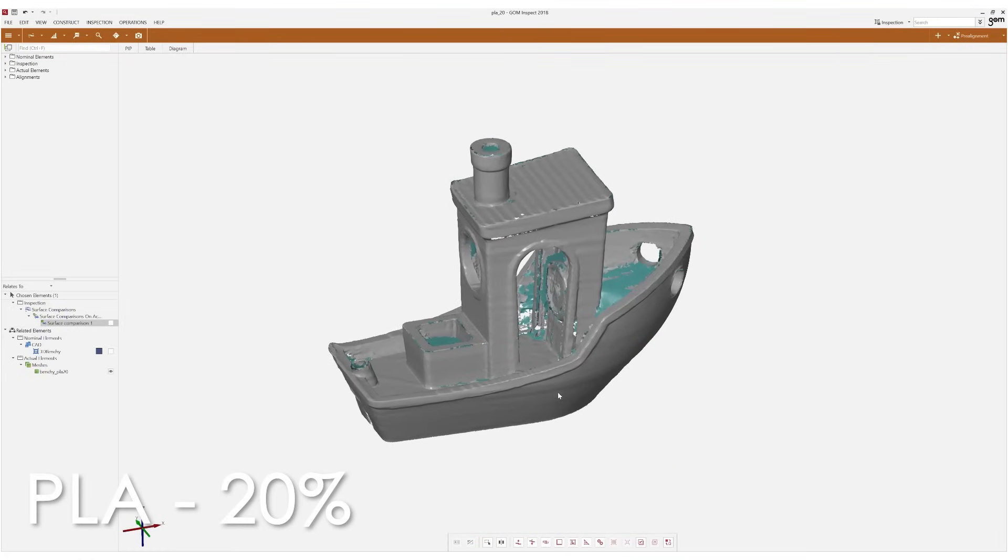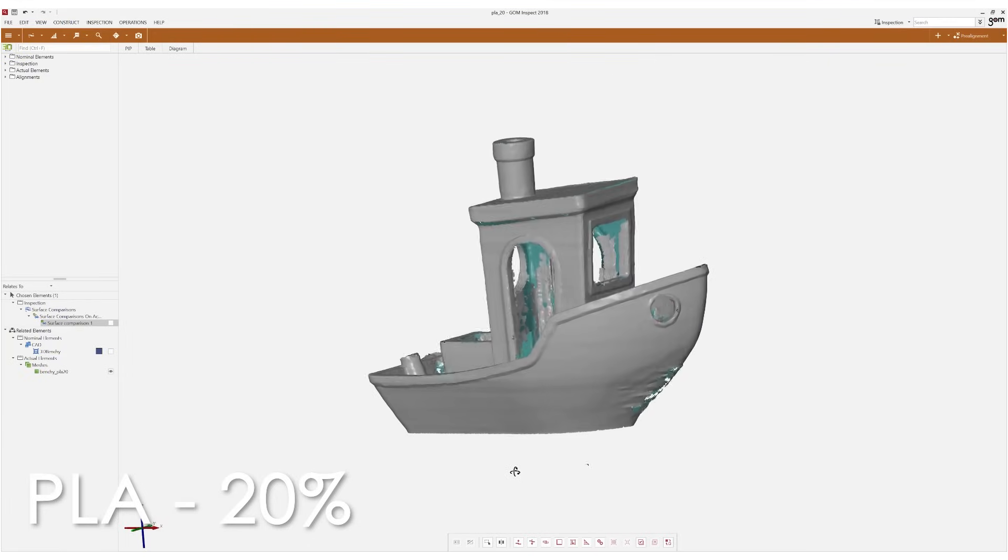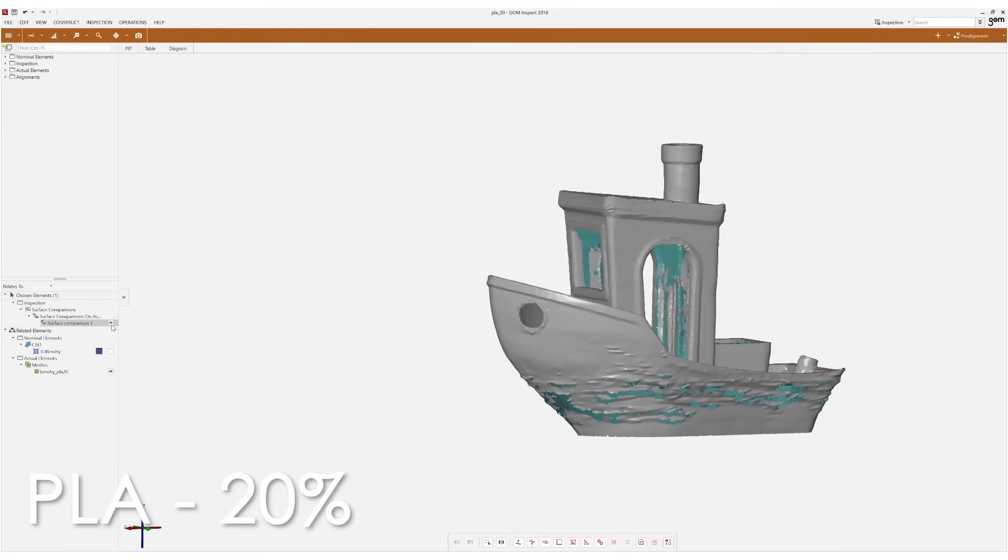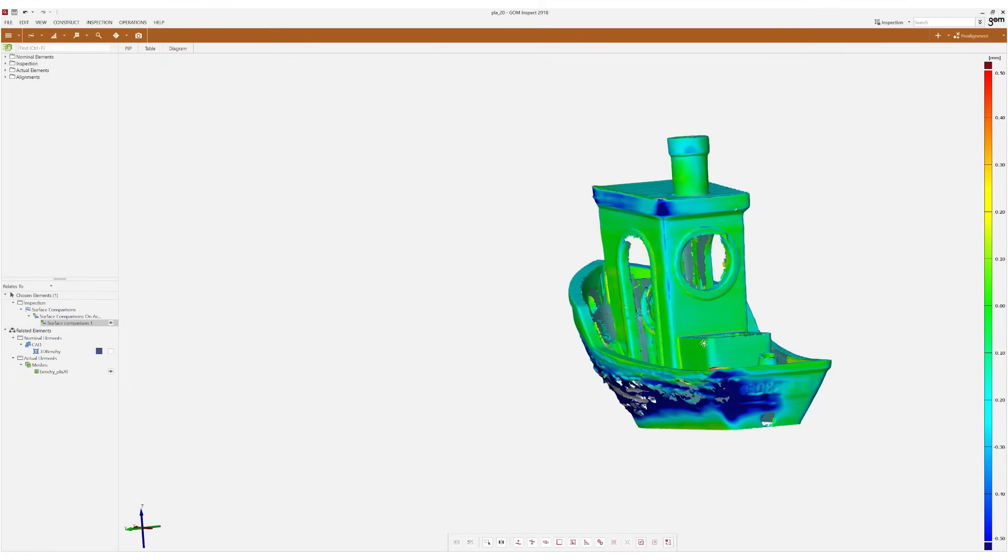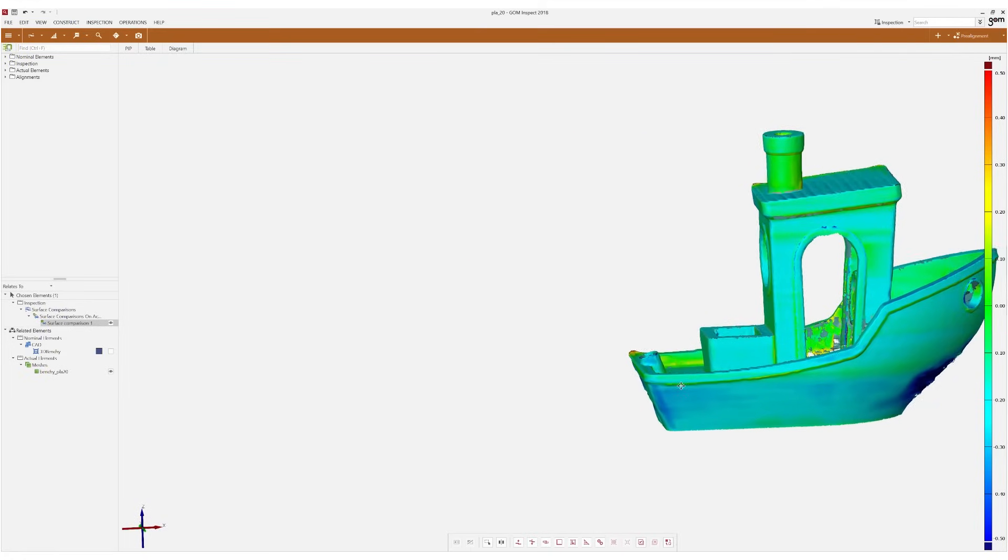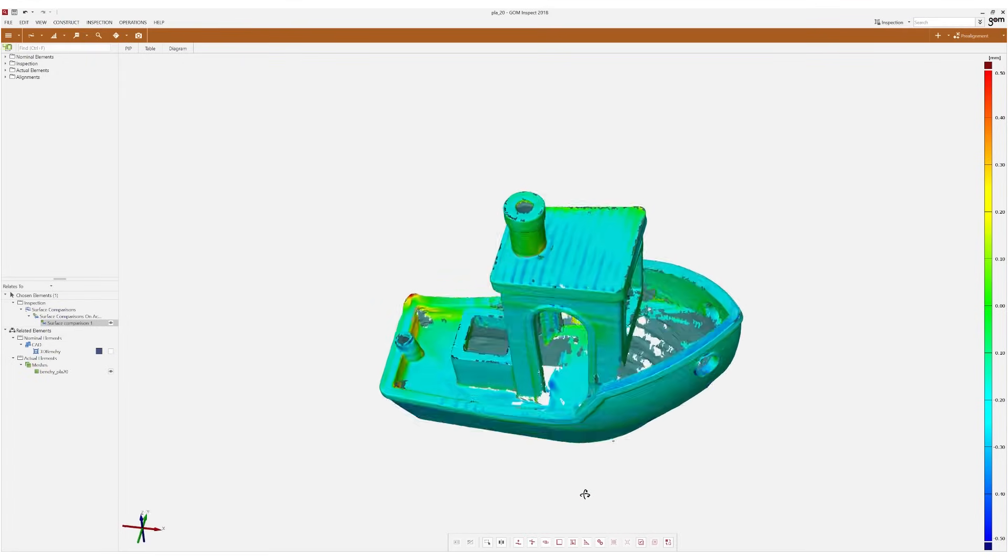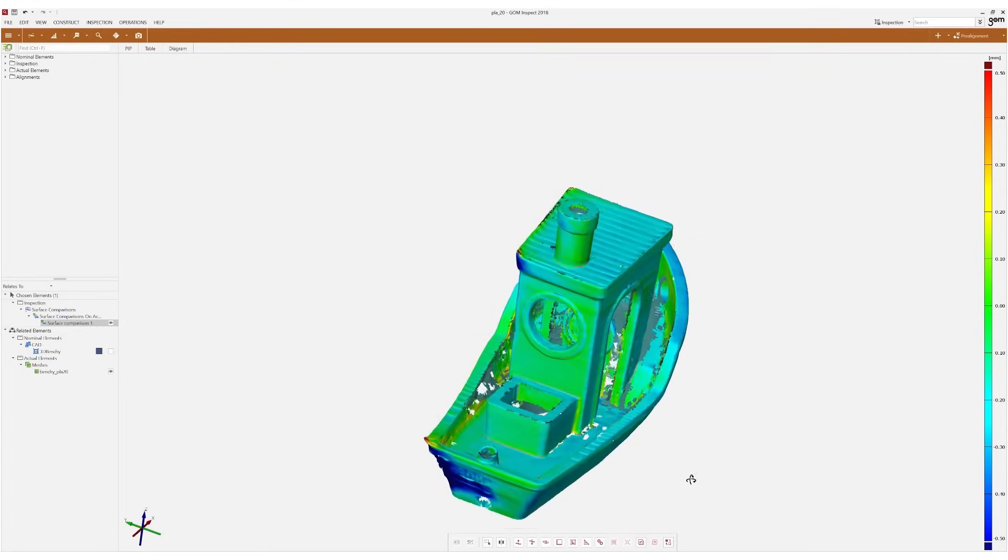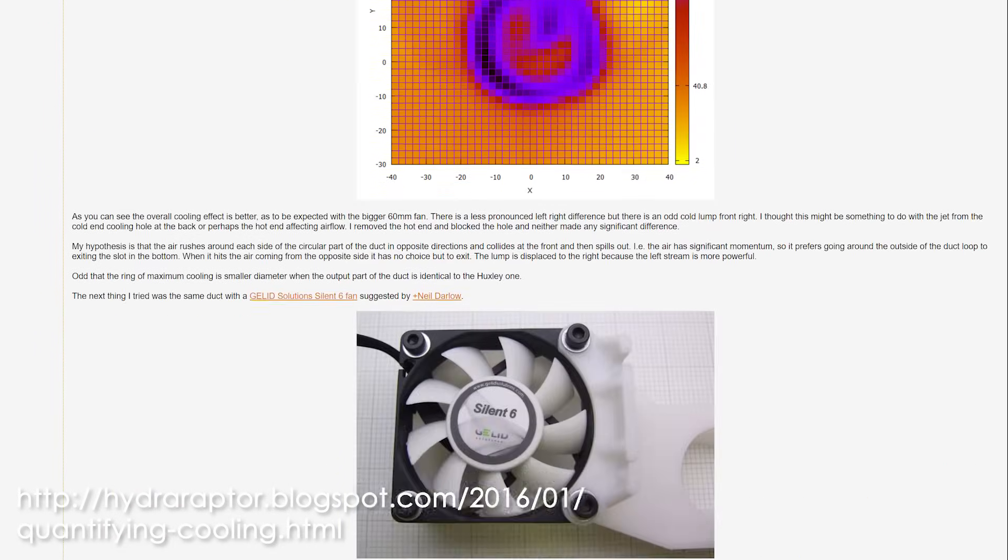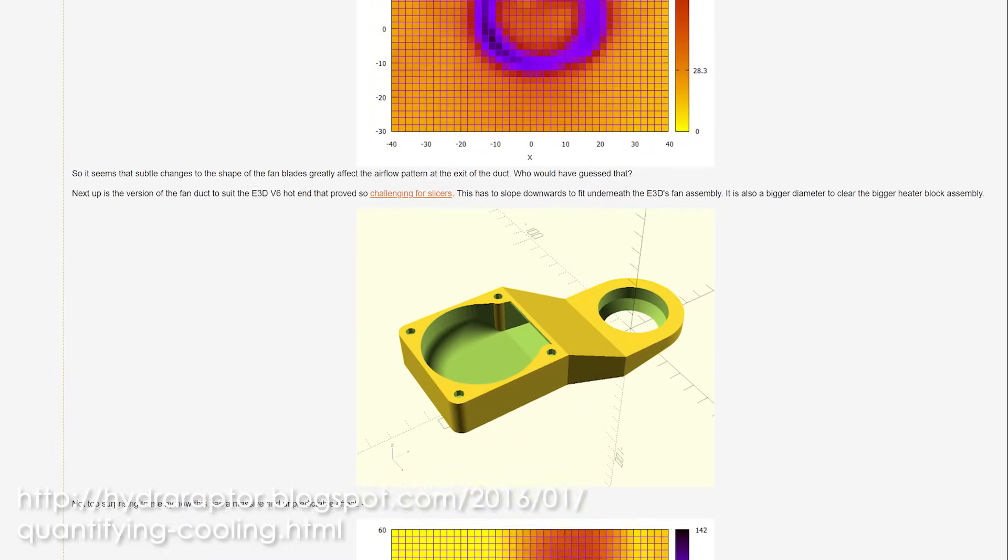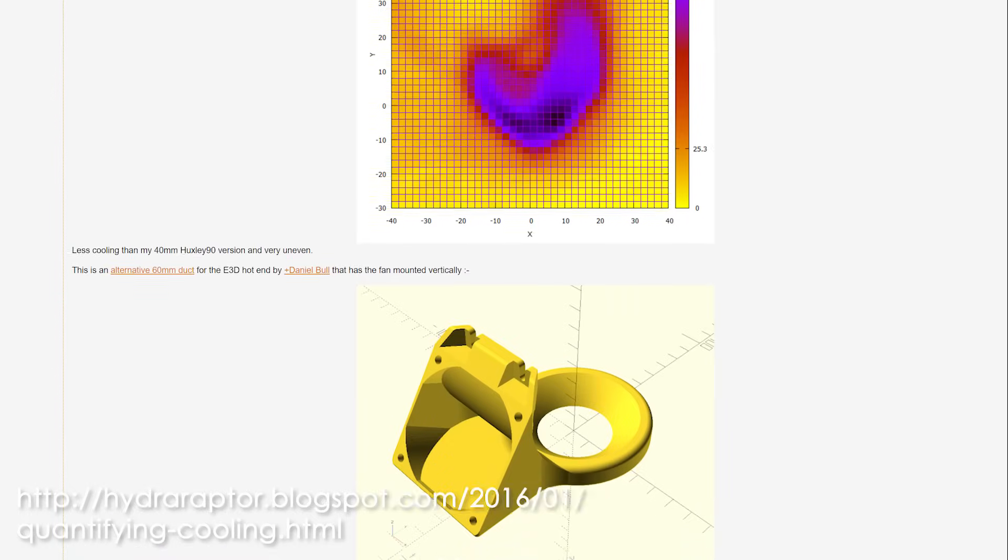The PLA Benchy at 20% cooling is even more interesting because it looks okay from one side but on the other side, which is the side facing away from the part cooling fan, is totally deformed. So it seems as if 20% cooling with the Prusa is still on the low side and it might be an interesting project to optimize the fan shroud so that it's more even in all directions. If you guys are interested in that topic there is actually a cool blog post by Nophead, the father of the Mendel 90, on the uniformity of different fan shroud designs. I'll leave a link down below.